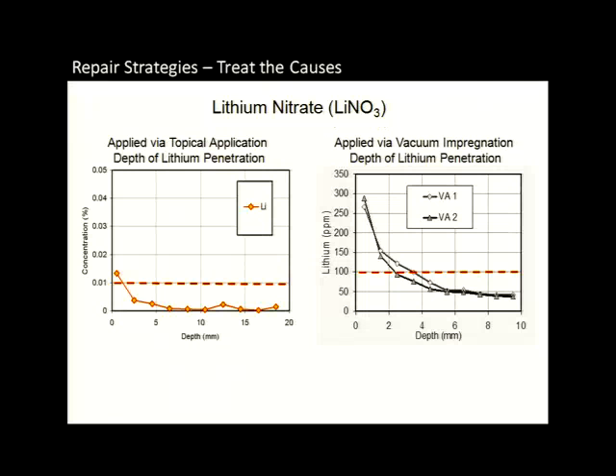So what I've showed here are two graphs. They're both showing the depth of penetration of lithium nitrate into the structures. So these are both from the Jersey barriers. This is in Leominster, Massachusetts, about an hour and a half outside of Boston. And the red dashed line shows you the concentration that we need to control the reaction, about 0.01% or 100 parts per million. And so what we did was we took cores on the concrete, we took them back to the lab, we profile ground them, and then you do acid digestion to see how much lithium is actually there.